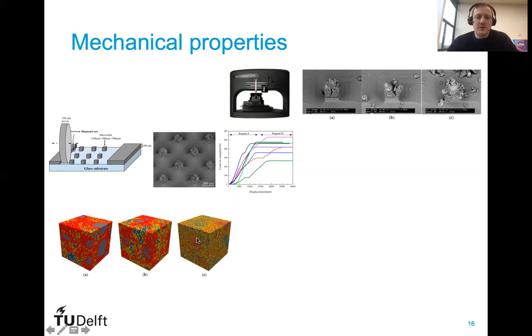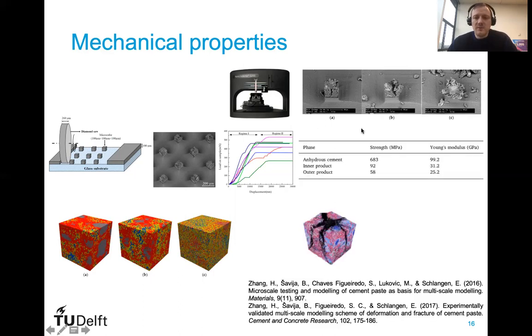So we created models with different water cement ratios, and we simulated them using the same loading and boundary conditions as given in the experiment. And with that, we could estimate the strength of different phases in our cementitious matrix. The stiffness we already knew from nanoindentation, so we had only one unknown. And assuming that the ratio between the strength and the stiffness is constant for different phases, we were able to estimate properties of different phases in the cementitious matrix.